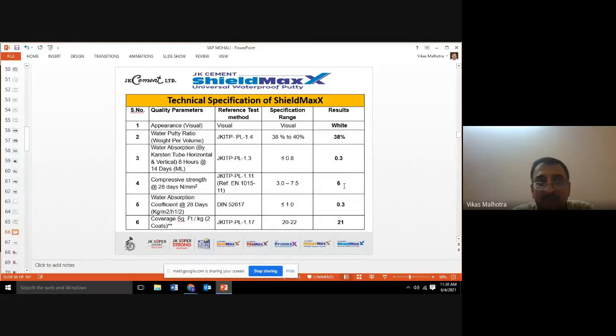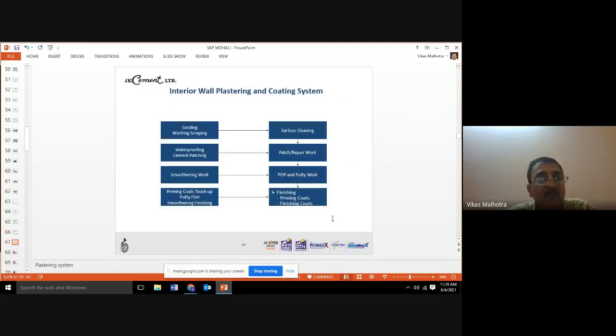Compressive strength is again 6 MPa, and coverage, you can see, it's not only the waterproofing property on which we have worked, we have increased the coverage also. Just to share with you, for Wallmax, the coverage is around 14 square feet per kg in 2 coats, whereas in this it is 21 square feet per kg. So almost 50% increase in the coverage.